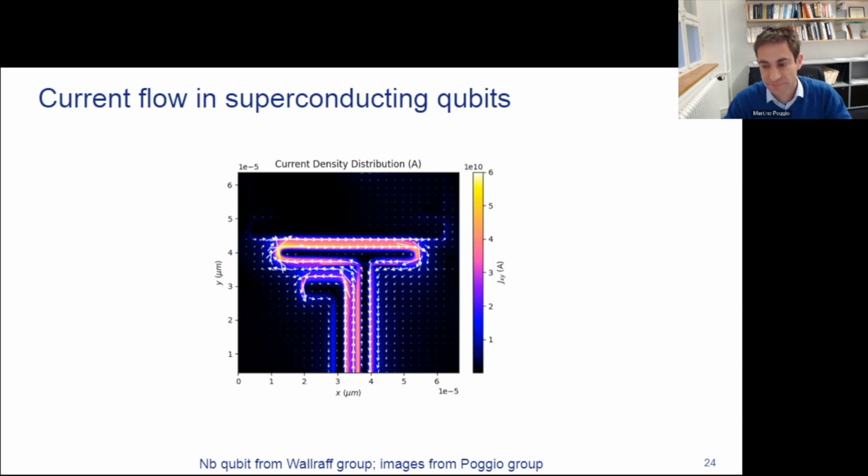So this is probably a question you faced before. Can the techniques you've talked about be implemented in a liquid medium or soft matter, for that matter? Right. Yes, so for the scanning SQUIDs, as the ones that I've presented, the SQUID on tips, I would say that it's very difficult, especially the lead ones. They oxidize. They need to be in vacuum in order to work. Of course, they need to be at extremely low temperature, so below the critical temperature. So I think for any kind of SQUID, that would be difficult.